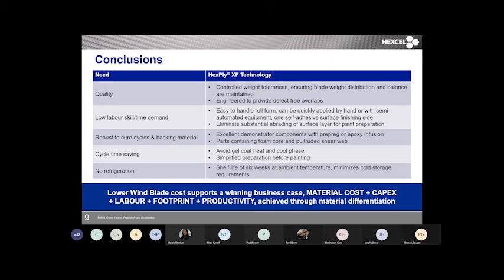We mentioned 2 hits on cycle time saving. So you're avoiding that thermal cycling at the start when it's in the mould, and also you're reducing your prep time. And people often worry about latency and storage when we talk about pre-pregs compared to infusion. So this system has 6 weeks out life at ambient temperature. So if you're building one blade every 24 hours, that's into a domain where you can have a just-in-time or a weekly, bi-weekly delivery and manage stock with no need for investment in refrigeration.